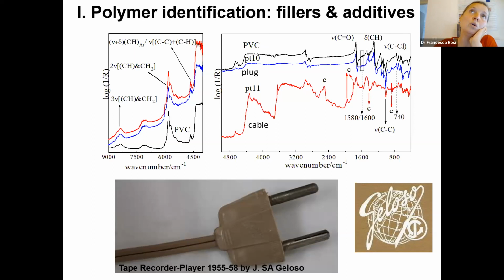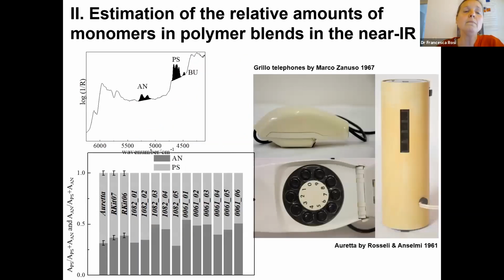This also allows me to show you another important point when we work in external reflection mode. It's very difficult to build up any kind of spectral database, because the same material, same sample and same compound can show different spectral profiles according to its morphology, and also according to its optical properties that can be modified by the presence of another filler, like in this case calcite. As I told you before, we wanted to go further than the simple identification of the polymer, and so, considering the fact that in the near infrared region we have generally no distorted bands, and also on the basis of the wide literature in which near infrared spectroscopy is employed for investigating plastics for other applications, we also evaluated the possibility of estimating the relative content of the different monomers in a polymer.